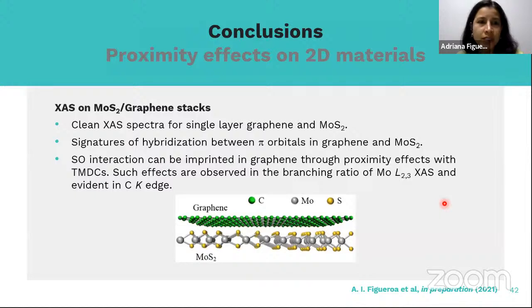So just to conclude this part, I just want to tell you that, on spin orbit interaction, we've used X-ray absorption spectroscopy. We observe very clean spectra for single layer graphene and single layer MoS2. We observe signatures of hybridization between the pi orbitals in graphene and the 4d orbitals on MoS2, and that there is a spin orbit interaction that can be induced in graphene through proximity effects, and those are reflected on the XAS, because we see changes in the branching ratio of the molybdenum, and they're also evident in changes in the carbon K edge.